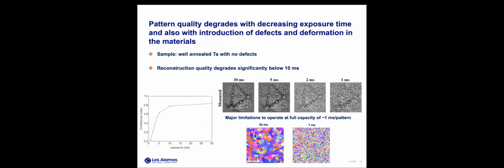And the other thing we wanted to look at was the level of noise in the experimental patterns. How bad can it be for us to still be able to reconstruct the diffraction pattern accurately? Usually the pattern quality degrades due to defect generation or imposed deformation. But here we have emulated that scenario by changing the exposure time used for collecting each EBSD pattern. Typically 30 milliseconds is used for EBSD data collection for a fully annealed sample, and the pattern becomes noisier with decreasing exposure time.